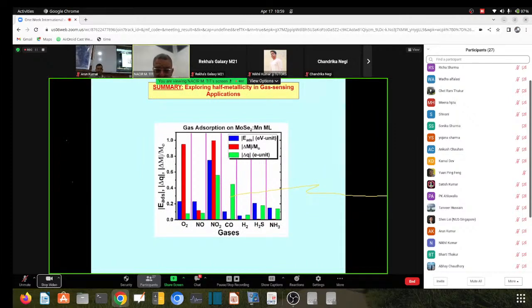So the conclusion of this second part, which I ran very fast, is that we plotted the absolute value of the adsorption energy, the absolute value of the charge exchange, and the absolute value of the relative change of magnetization. So we can see here, over all the 7 molecules studied in the adsorption study that we did, that there is a kind of tendency towards selectivity toward NO2, because the huge change is attributed to those molecules. On 3 aspects, adsorption energy and the relative change of magnetization, it's huge, almost 100%, and also delta Q, the charge exchange. So our expectation is that NO2 should be selected, if you use MoSe2 doped with Mn. We are not exploring different systems, only one case.